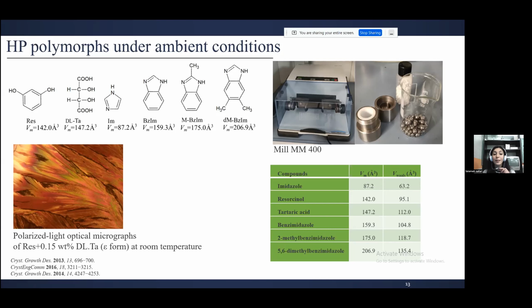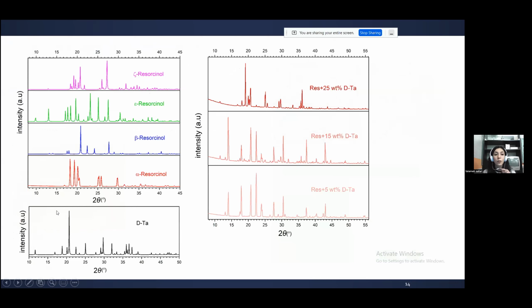And in the next step, what we did, I tried to do the powder diffraction. So you can see here the pattern of the resorcinol for different phases, which I, of course, generated from Mercury, because I had all of them from the single crystal data. And you can see how epsilon is really different.